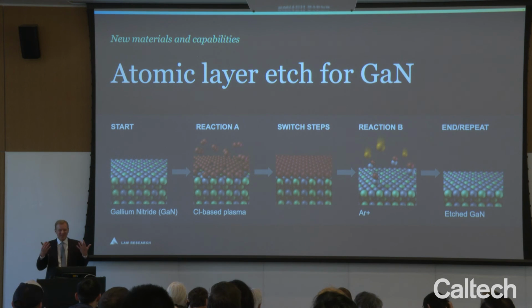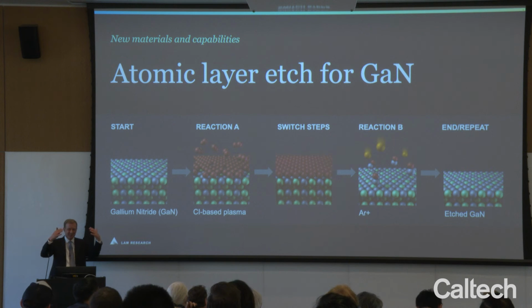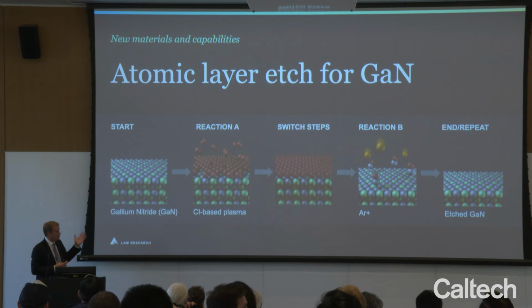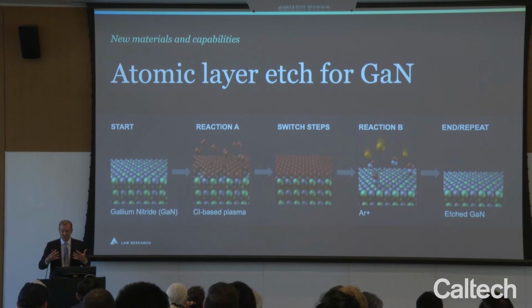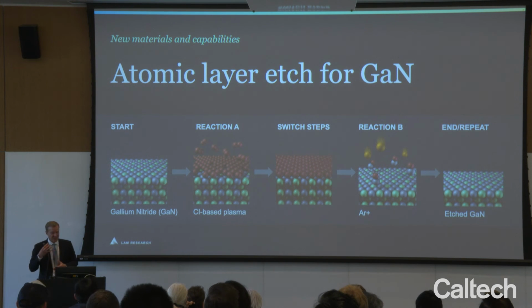So if we come all the way back to Feynman, and I think mostly Feynman was talking about building things at the atomic scale, but what Austin and I are talking about is how to reverse that process and actually deconstruct and perform etching atomic layer by atomic layer. And so we do that through this process, as he described, of fast cycling of alternating surface reactions. And it provides us a really very finely controlled capability to etch the wafer. And in this case, I'm showing an example of gallium nitride etching.